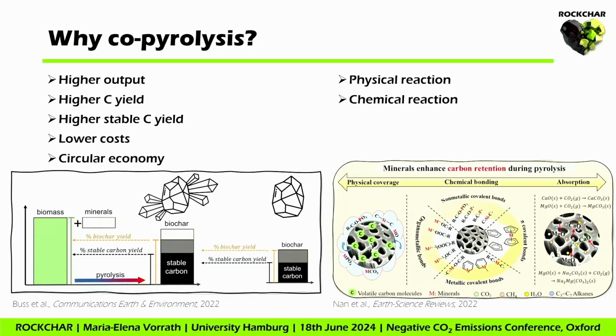And the reason why you have more carbon in your biochar has two reasons. You have a physical and a chemical reaction. So the physical reaction, and therefore I pelletize it, is just that the minerals have a protective layer around the biomass and protect it from outgassing during the pyrolysis. And the second one, this is very important, if we have ions that are available, they can make new bondings with carbon, like metallic or non-metallic bonds, and then we have more carbon, magnesium-carbon bonds, for example, and this leads to a smaller outgassing of carbon as well.